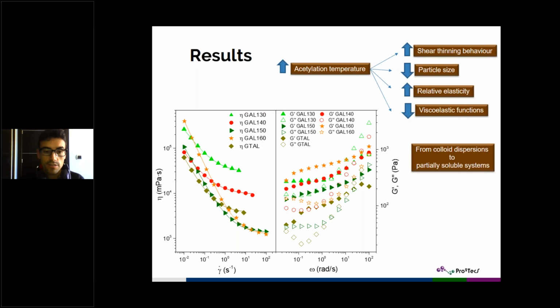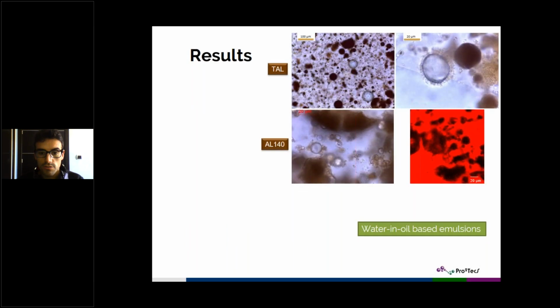So after that, as we wanted to try if with this acetylated lignin that was able to thicken the oil, to structure the oil, we could use it in a completely different approach. That is the use of this acetylated lignin as a Pickering emulsifier. As lignin has been used quite a lot for oil in water emulsion, what we tried in this study was to get at least some preliminary result of water in oil-based emulsions, as that one I show you here in this picture.